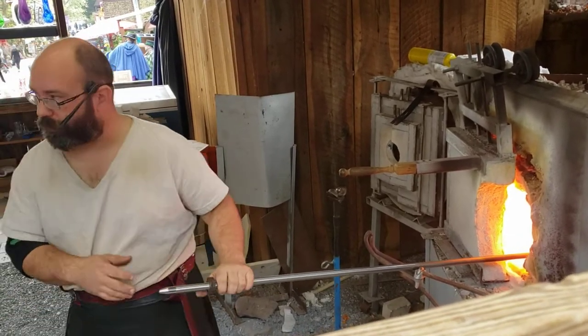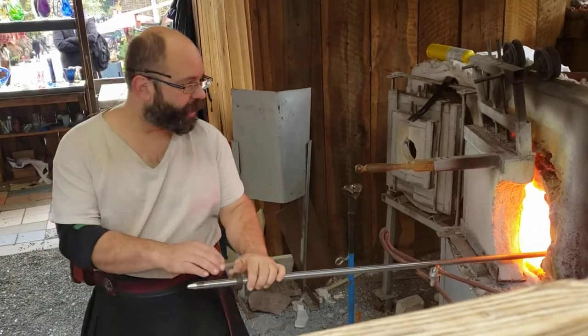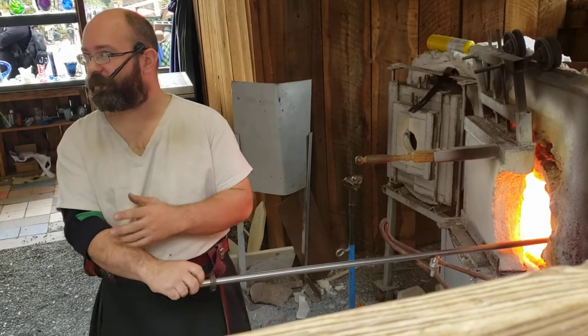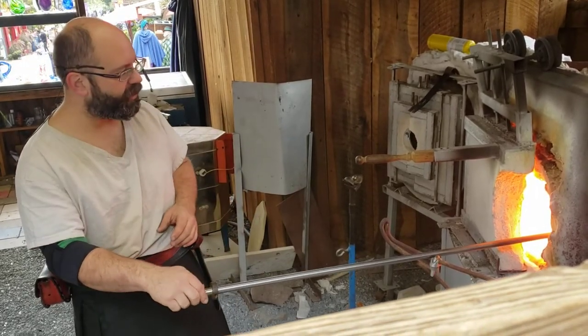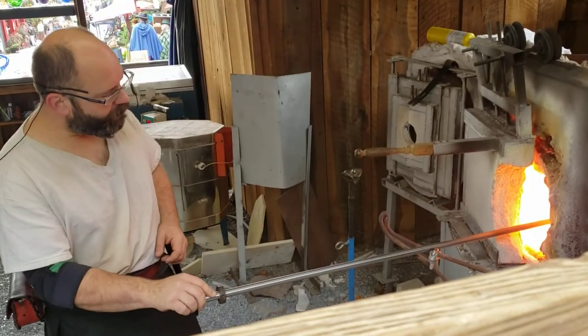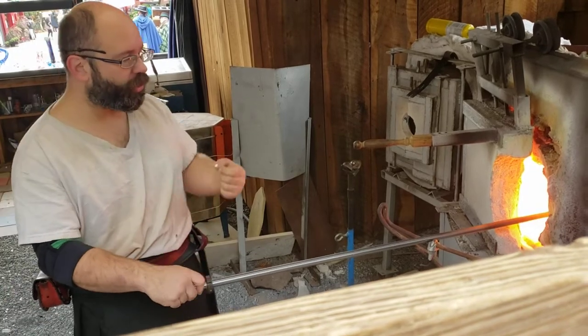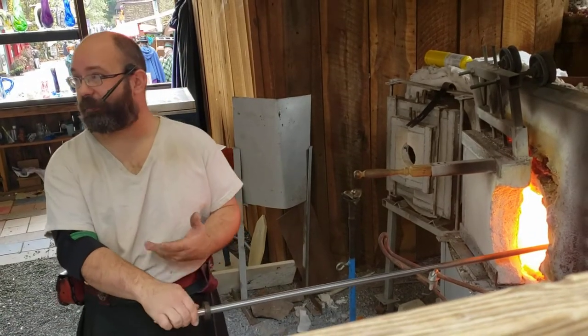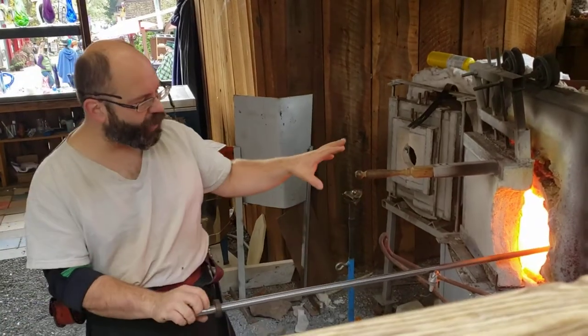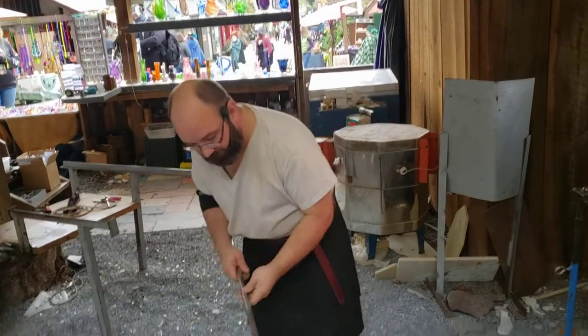Small air bubbles are not structural flaws — I quite like the way they look. Some people might consider them optical flaws, but that really depends on the period of time you're talking about and the type of work you're doing. But large bubbles can be structural flaws. They can get too close to the surface and blister, then crack and pop and leave little sharp edges on the surface of your piece. So melt away the texture on that glass, but leave the movement in the color.